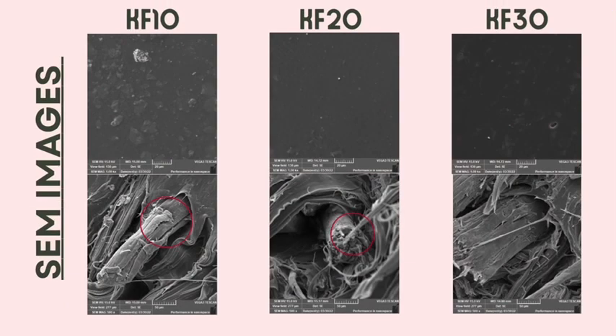The SEM results showed that PBAT only coated the Kenaf fiber as shown in the reticle of the KF10 image and made the biopolymer stronger. When force was applied, we can see that the bonding process occurred and resulted in a cut-off of the bonding, which broke as circled in the image under KF20. The optimal percentage of Kenaf fiber composite for production was found to be 20% or KF20 because it had the smoothest surface, likely due to better compatibility and integration between Kenaf fiber and PBAT.